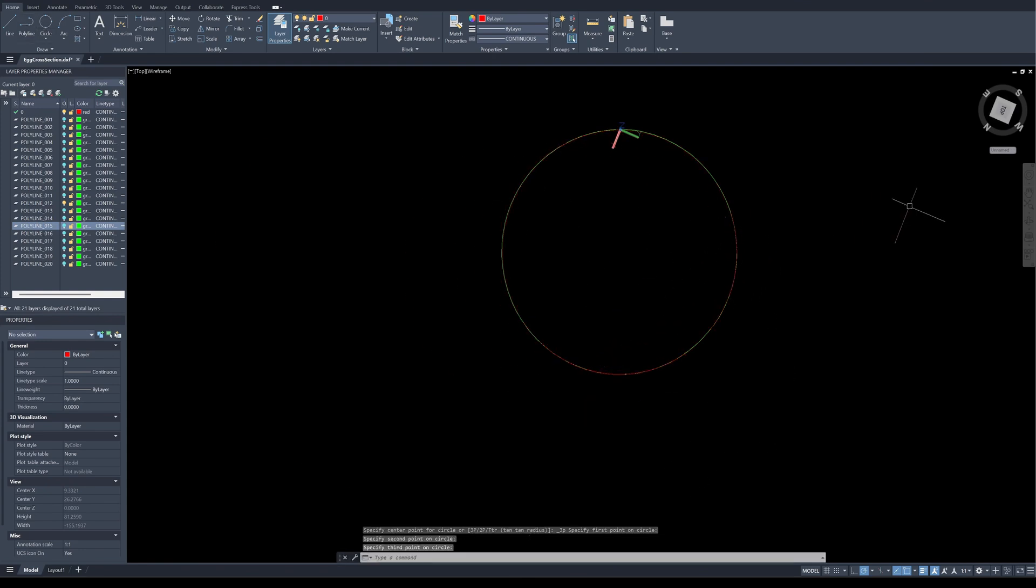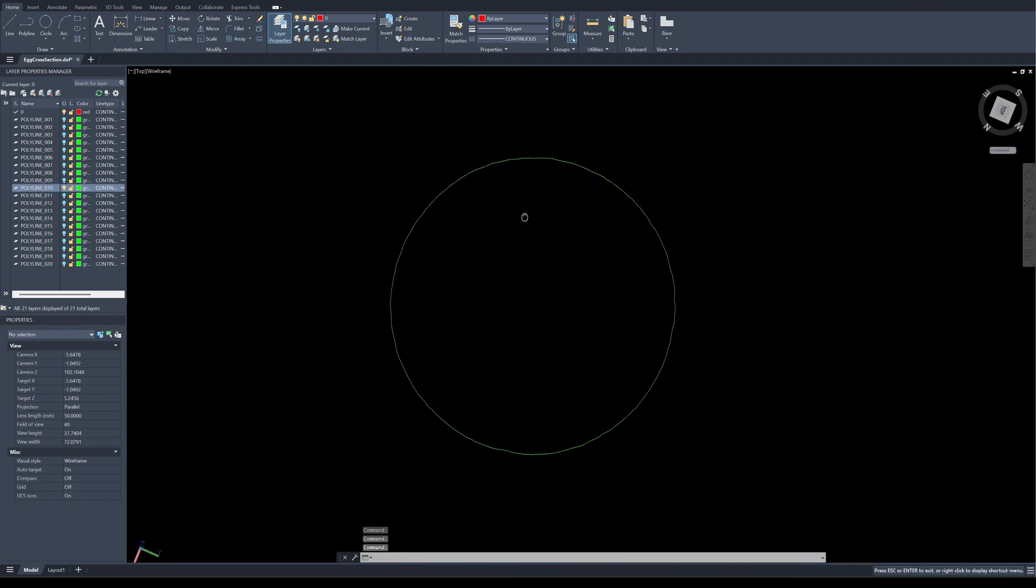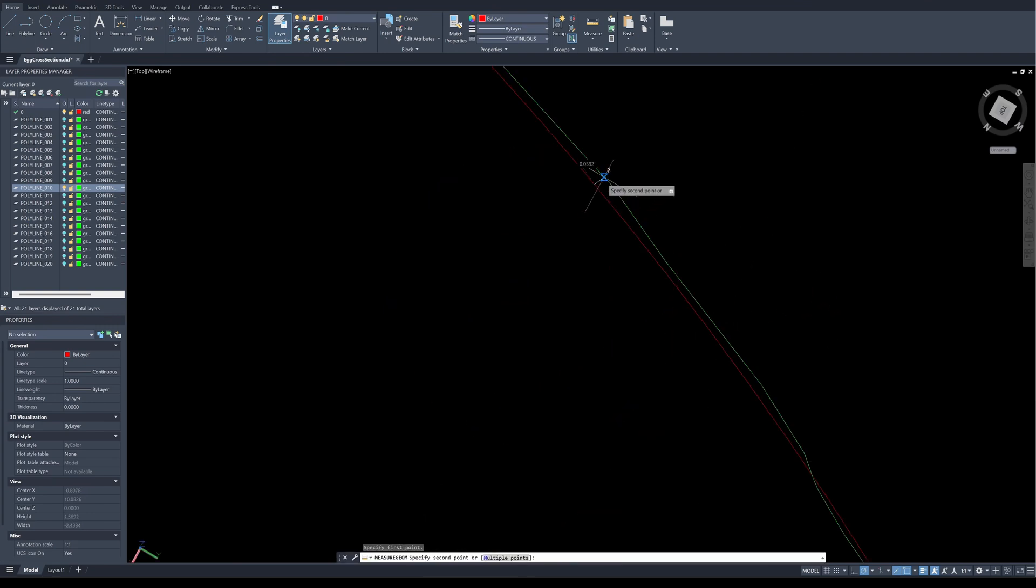Okay, let's move to the upper cross section, the smaller ring. I do the same, draw a circle with three points. First measurement 63 micron and on the other side is 48 microns, so the egg shape is more circular along the upper and lower part. Let's move to another ring, upper section. I do the same, three-point circle: 57 microns, 39 microns.